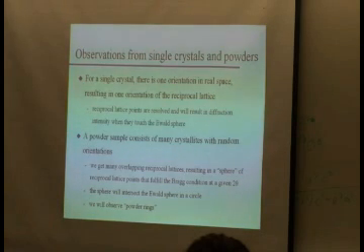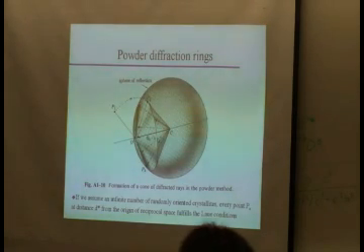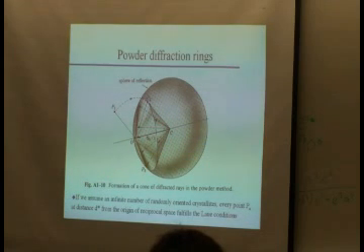So, what you will see in a powder experiment are so-called powder rings. Okay? There's an example of that. Here's that sphere, that circle that intersects. Now, if you've ever worked with single crystals before, you may have had something and there were some rings showing up on your diffraction pattern, and your crystallographer said, gee, you brought me a powder. And if you knew nothing about reciprocal space, you were probably scratching your head thinking, what are they talking about? That's what they're talking about, okay? If you see rings, they result from a powder.